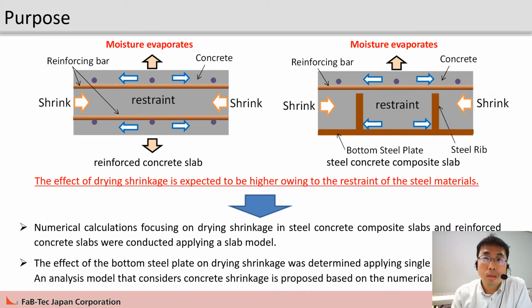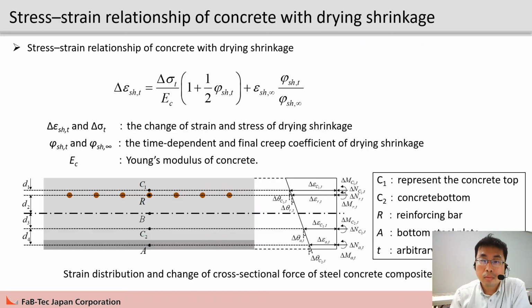concrete composite slab. Numerical calculation focusing on drying shrinkage in steel concrete composite slabs and reinforced concrete slabs was conducted applying a slab model. The effect of the bottom steel plate on drying shrinkage was determined applying single slab specimens. An analysis model that considers concrete drying shrinkage is proposed based on numerical results. The numerical calculation focusing on the time-dependent behavior of drying shrinkage in steel concrete composite slabs and reinforced concrete slabs was conducted applying a slab model.